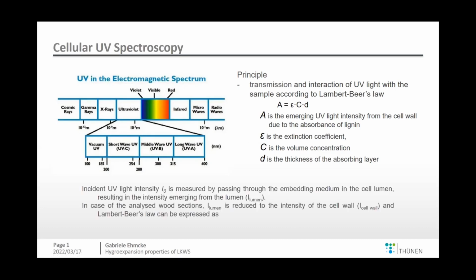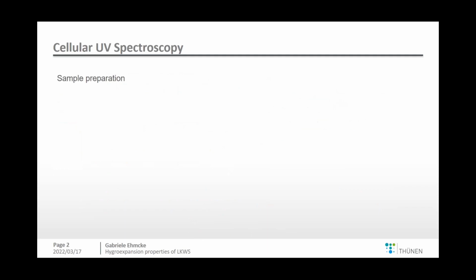So when we transfer this principle to the wood cell walls, we talk about the intensity that is measured by passing through the embedding medium and the cell lumen. It's called I0, and the energy that is passing the cell wall layers. And we have this basic equation from the Lambert law, and we get the absorbance A, derived from the logarithmic value of the emerging intensity from the lumen divided by the emerging intensity of the cell wall. These are the physical backgrounds.